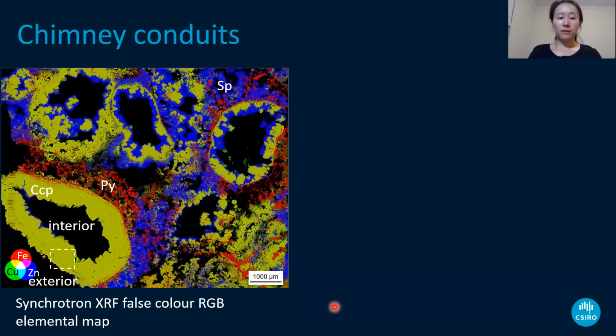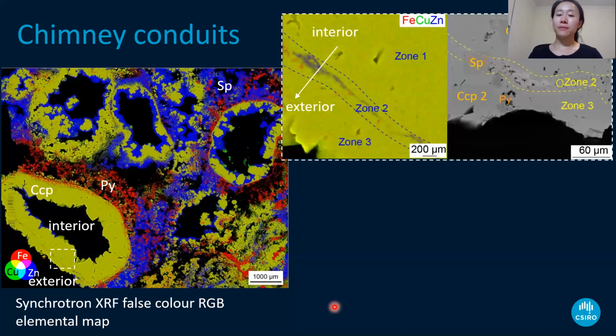If you take a look at this region and zoom in, it looks quite simple from a central image, just dominated by chalcopyrite, yellowish here, and segregated by gaps. However, the SEM image shows that the gap actually contains a lot of sphalerite here and also some native gold.